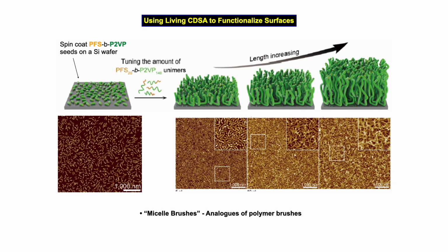Finally, one application that we've been looking at is to functionalize surfaces using living CDSA. What you can do is you can spin coat seeds that you make by sonication onto a surface, as you see here. Now they're stuck to the surface. If you now add polymer to the surface, it will grow from the seeds, and you can grow brush layers from the surface.